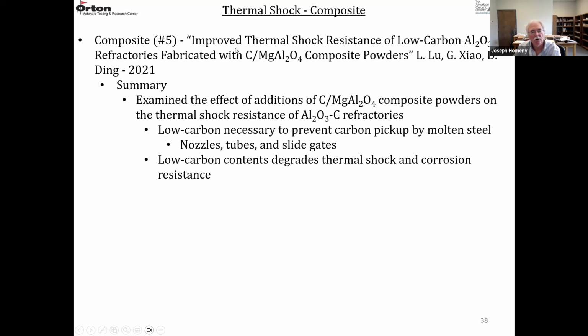This other work improved thermal shock resistance of low carbon aluminum oxide carbon refractories fabricated with carbon spinel composite powders. So they looked at the effect of additions of carbon spinel, and spinel is MgAl2O4, composite powders on the thermal shock resistance of alumina carbon refractories. So these are low carbon composites, and they're low carbon because they want to keep the carbon content low to prevent carbon pickup by molten steel.